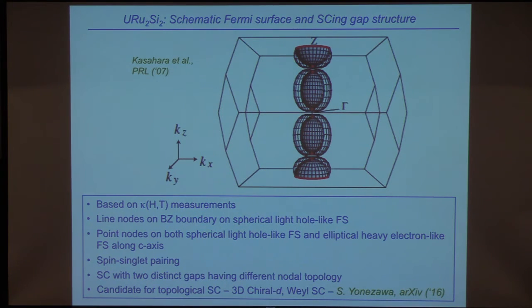Let me just say a little bit about the superconductivity. This is based upon thermal conductivity measurements in a field and as a function of temperature. So this has line nodes on the Brillouin zone boundary on the spherical light hole-like Fermi surface. So this is a spherical light hole-like Fermi surface. This is a line of nodes. And then you have point nodes on both the spherical light hole-like Fermi surfaces and elliptical heavy electron-like Fermi surfaces along the c-axis right here. So these are the point nodes. So these are the Fermi surface sheets. And then these are supposed to represent the energy gap, okay? And you have spin singlet pairing and basically superconductivity with two distinct gaps having different nodal topology. And as I said before, this has been suggested to be a candidate for a topological superconductor.